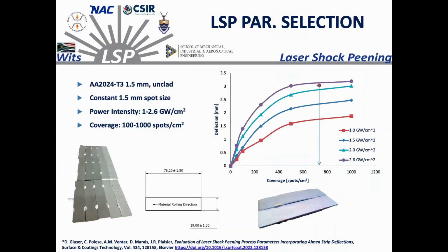So there are a lot of other toys that are included in the panel that are not shown in the picture. So first things first, we need to start to select some parameters, because we have a range of parameters that we can use with the units that we have and the monitoring system online. So we decided to keep the spot at 1.5 millimeter, and thanks to the energy attenuator that we have, we can change the energy without any problem up to 2.6 gigawatt per centimeter square. And also the coverage, so how many spots we put per square centimeter, we can change within a certain range.